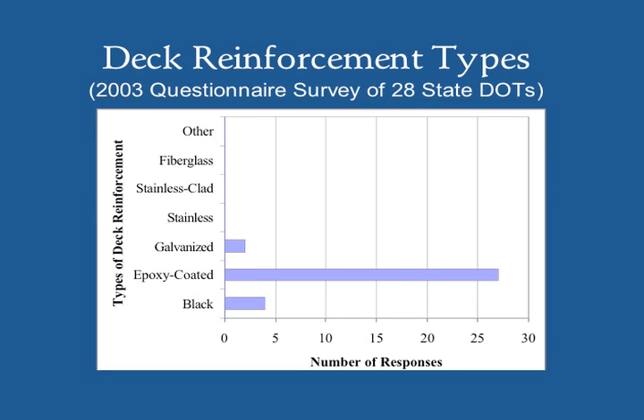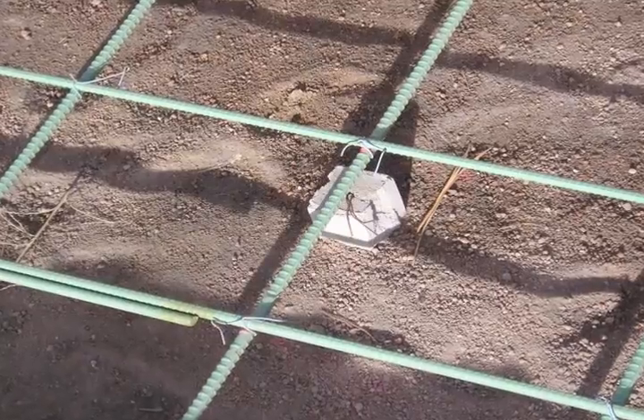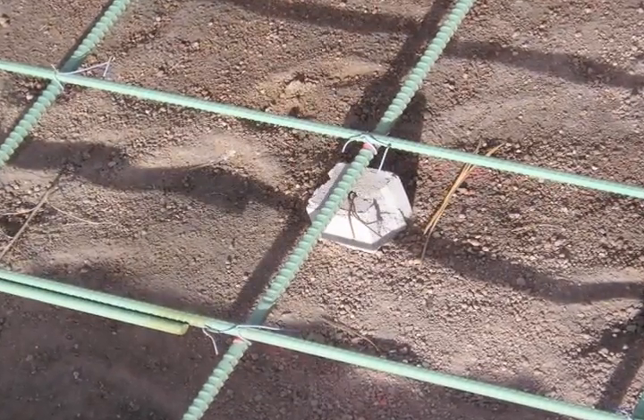To answer this question, let's talk about the type of reinforcement that's available. Again, these are results from the questionnaire survey of several state DOTs. You see that many DOTs use epoxy-coated rebar. This is commonly recognized by its green color. As long as the epoxy coating is intact, that is, no defects, no holes, no scrapes, the epoxy will prevent the chlorides from coming into direct contact with the steel and thus prevent corrosion altogether. However, for this to be successful, all parties involved with transportation, handling, and placement of this must be careful. And even with field cuts, such as is shown here, an epoxy compound patch must be applied to prevent localized corrosion at that location and ultimately shearing of the bar.